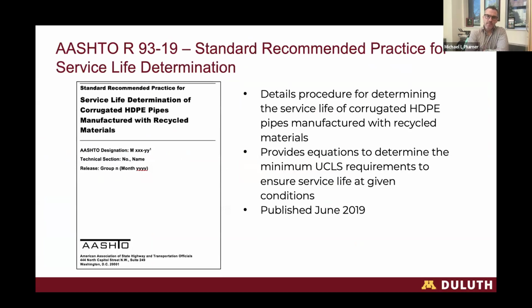And the end result ended up being a number of publications. One of the things that I think was really beneficial was this AASHTO publication, which is a standard recommended practice for determining the service life of corrugated pipes manufactured with recycled content. This would allow any pipe manufacturer or any state DOT to take a sample of their pipe material, assuming it has recycled content in it, and predict how long that material will last in that given installation. So even pipes that are poorly installed or have an excessive deflection, we can then correlate the service life of that product given the material properties.